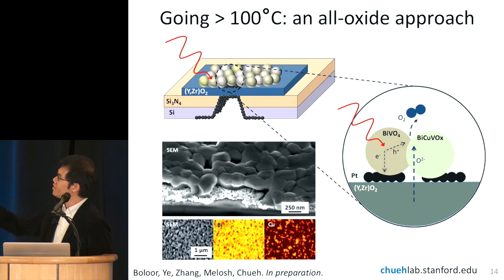And this is the type of cell that we have prepared. My student Madur has been working very hard over the past few years to make this happen. We're using as a demonstration system yttria stabilized zirconia as an oxygen ion conductor. We fabricated a very thin membrane on the order of a few hundred nanometers, which is supported on a silicon substrate, but this is not photoactive in this particular setting. The scanning electron microscope images and the chemical map below show you the cell from the top.